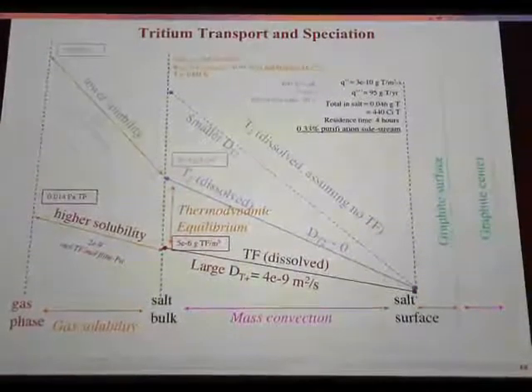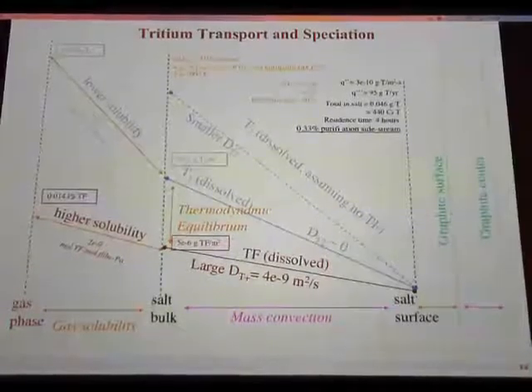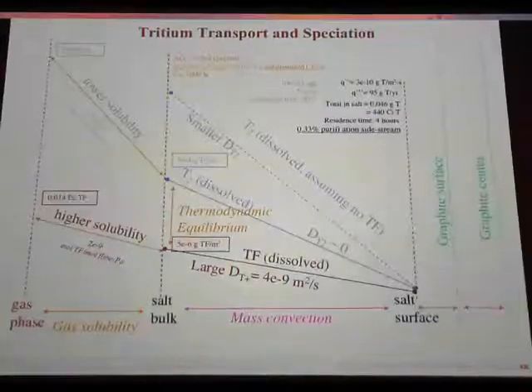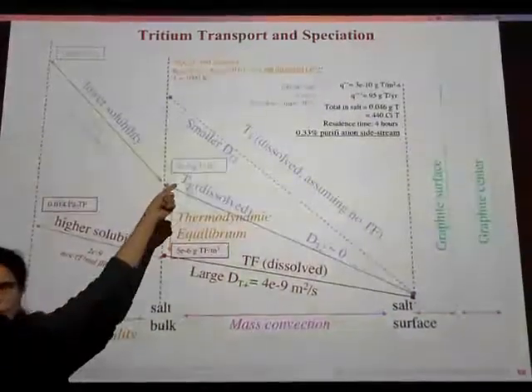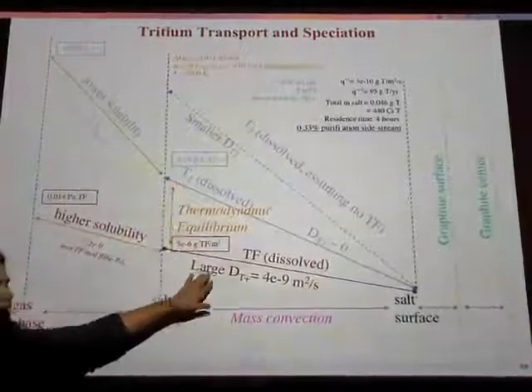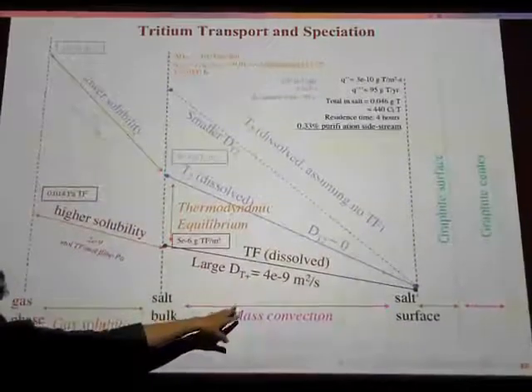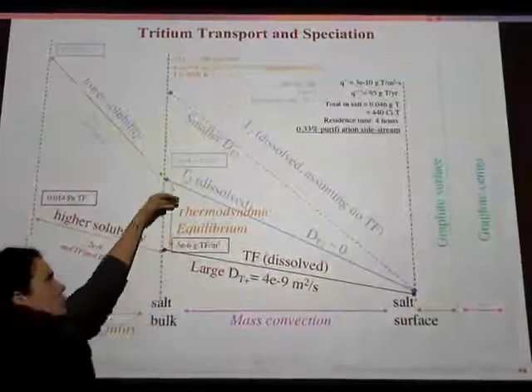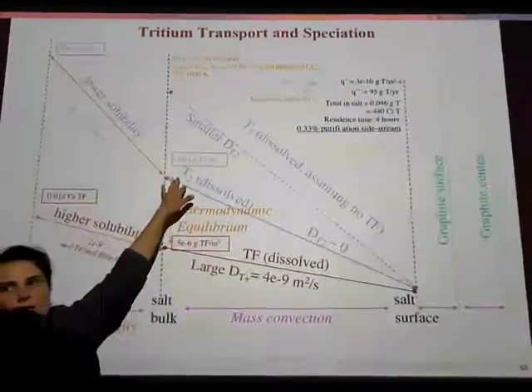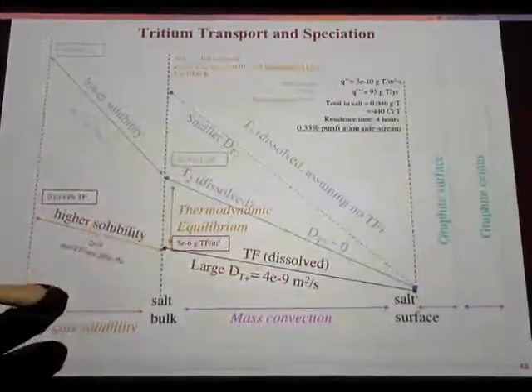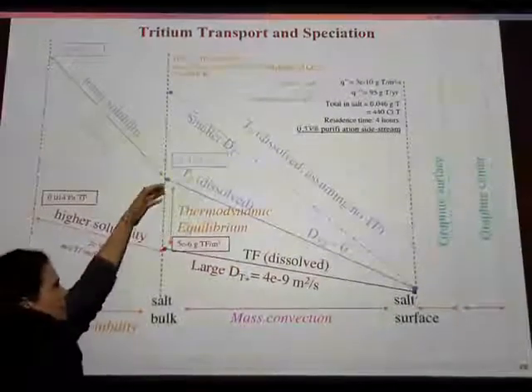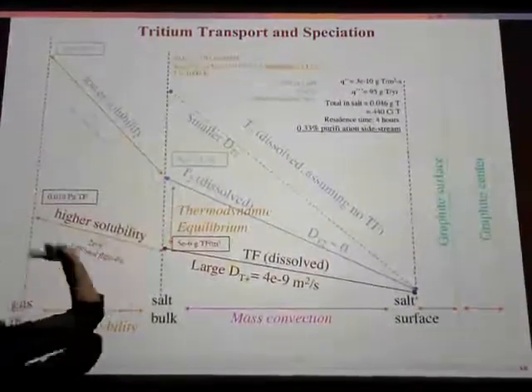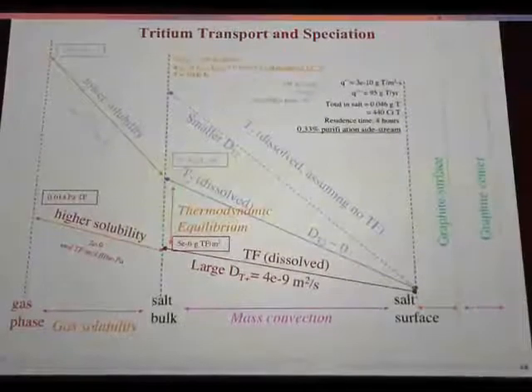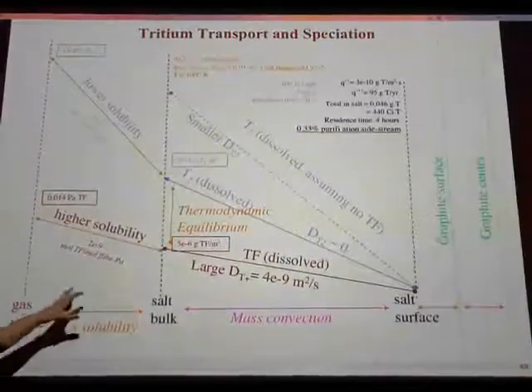But the main takeaway here is that tritium transport is tightly coupled to chemistry control, which is tightly coupled to corrosion. And T2 is the one that diffuses through the metallic components. TF does not diffuse through metallic components. And so if you're controlling your chemistry to be more towards this side, that means that you're going to have a higher driving term for leakage out the heat exchanger. So maybe we can play with the chemistry. So it's different in the heat exchanger and it's in the core. I don't know. But it's a degree of freedom that we have to consider.